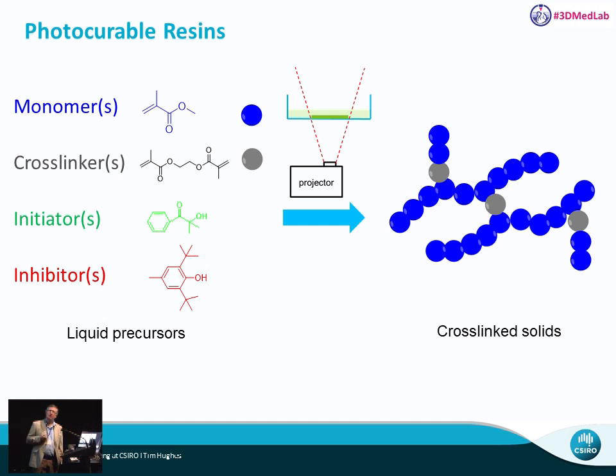Then we have additives. We have additives like initiators to start the chemical reaction. Typically that's a photoinitiator, and that's an example one there. And we also have other additives to stop the reaction. So we have inhibitors, or UV blockers, or UV absorbers. So it's quite a complicated mixture. And they're all mixed together as a liquid. And then we expose it to light using, in the case of DLP, a projector. And we're making cross-linked solids.